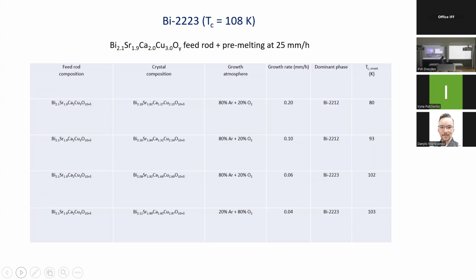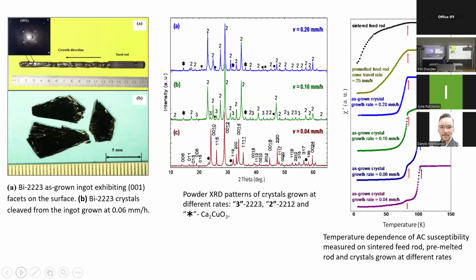of bismuth 2223 crystals. And here it's a typical grown ingot. It was prepared at 0.06 millimeter per hour. It means 1.5 millimeter per day, and the total length is 12 centimeters. So the growth takes several months. It's a very time and labor consuming process. Nevertheless, at the end, you could see relatively large facets. The lower picture is taken from these facets, and here are the crystals cleaved from this ingot.